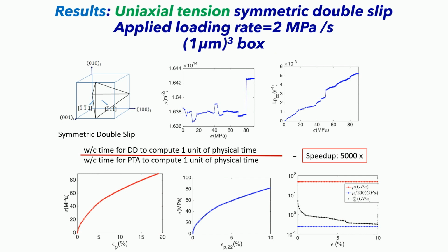So we set up a double slip configuration, uniaxial tension, double slip. Okay, and then you do stuff, and you're loading it at 2 MPa per second. This is load control, giving loads and stress strain curves. There are no constitutive equations. Everything is just inside DD, right? You're just averaging by this scheme.